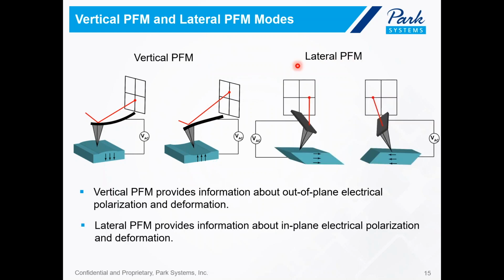And then we also have lateral PFM. From its name, it's very obvious that in lateral PFM, we essentially are looking at the lateral rather than the vertical components. As you can see, we are looking at the signal that is parallel to the sample surface. So you can imagine that the material may shear in plane, parallel to the sample surface. So this information allows us to gather in-plane electrical polarization and deformation in the phase and amplitude signals, respectively. This directionality allows PFM to provide information about the directionality of the strain and polarized domains.